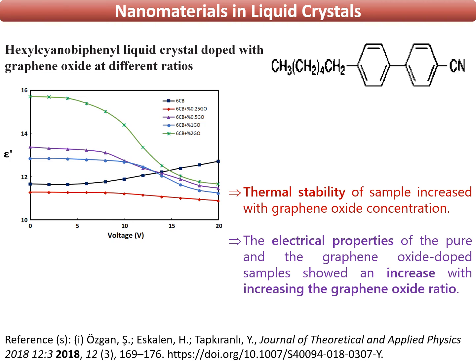In this example, hexylcyanobiphenyl-based calamitic liquid crystals were doped with graphene oxide at various concentrations up to 2% of graphene oxide. As can be seen from the figure on the left side, the electrical properties of the graphene oxide doped sample were higher as compared to the pure sample. It was also observed that the thermal stability of the sample increased with graphene oxide concentration.